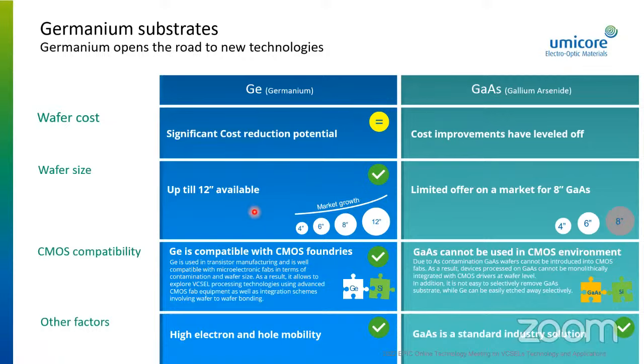So now, in terms of wafer size, I mentioned that germanium wafers are available up to 12-inch. So with Umicore, we can manufacture 12-inch wafers. We don't do it at scale because right now there is no demand, but it is possible. And one of the reasons, again, is just because it is very similar to silicon wafer manufacturing. With gallium arsenide, there is a limited offer on the market for 8-inch gallium arsenide, not talking about 12-inch wafers at all. Now, there is another factor which I think is rather interesting, related to CMOS compatibility.